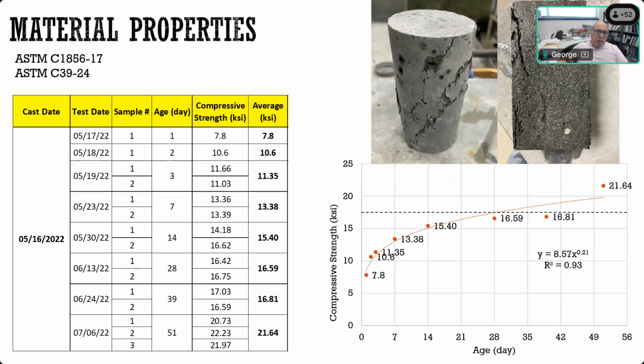And it is actually showing you the failure of the specimen under that high load. It does not have the same conventional failure that you get when you test the cylinder. You don't form a cone or big cracks, or get it completely fragmented, but you basically get just the cracks and the fibers holding it together. You can see also the fiber distribution across the section. That's what gives it the ductility that you need and prevents it from having a sudden failure.